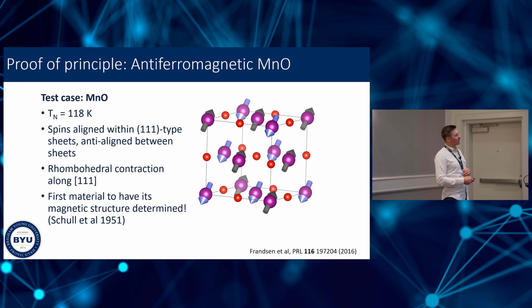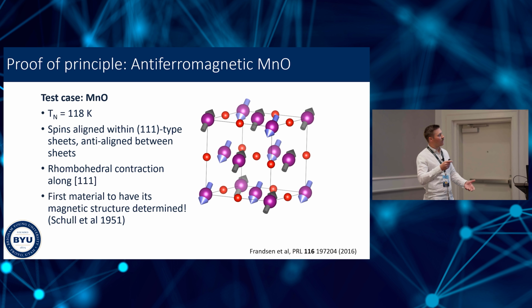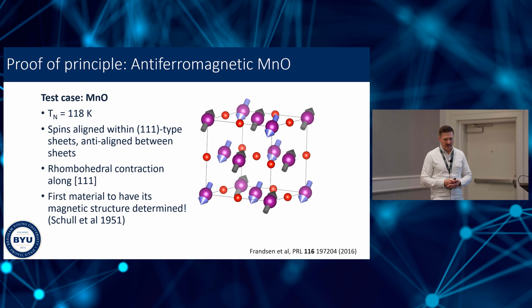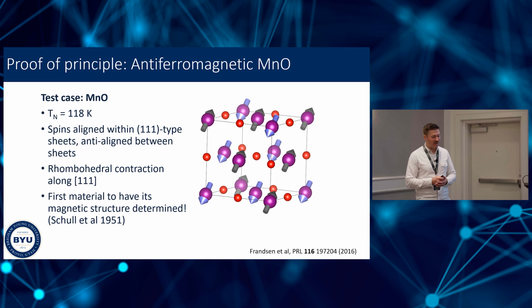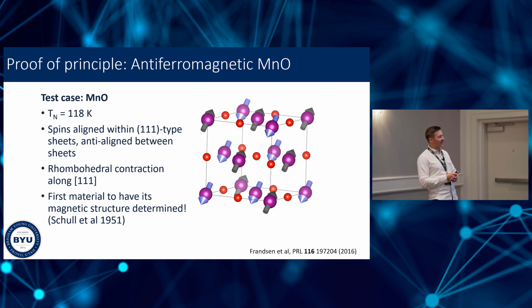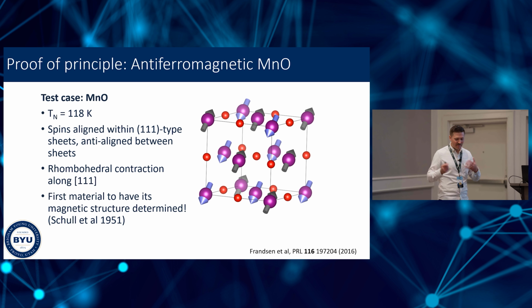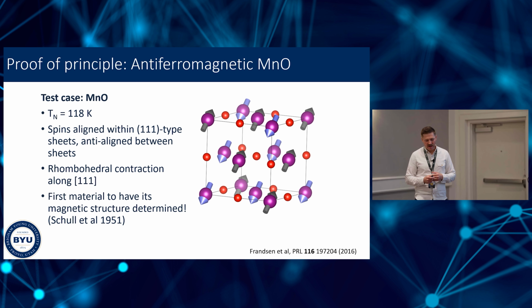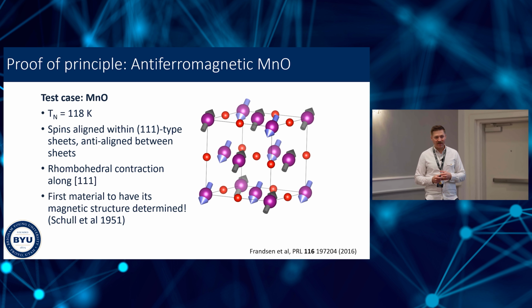Turns out that there's also a rhombohedral contraction of the lattice along the 1-1-1 direction when the material undergoes that magnetic transition. It happens to be the first material whose magnetic structure was ever determined by neutron diffraction. That was the work of Cliff Shull in 1951. So it's kind of fun for us to revisit this historical material in the context of magnetic PDF.